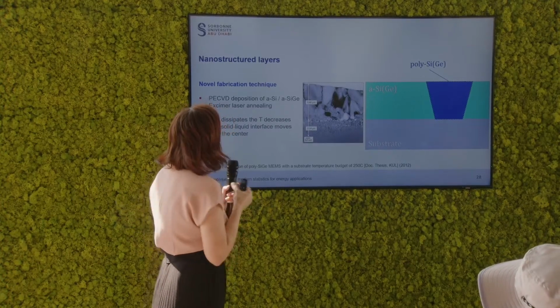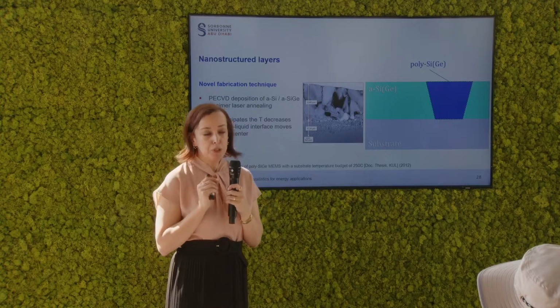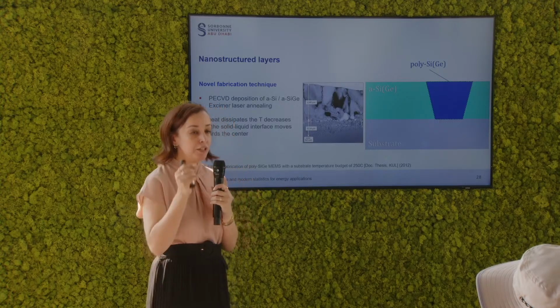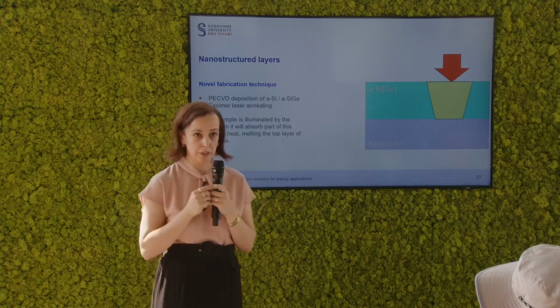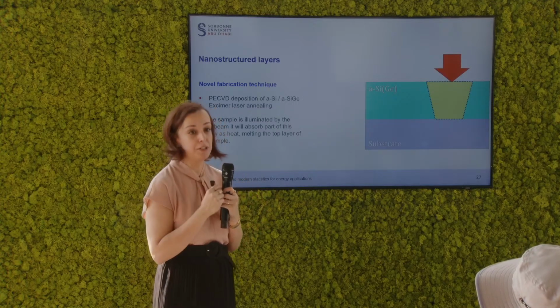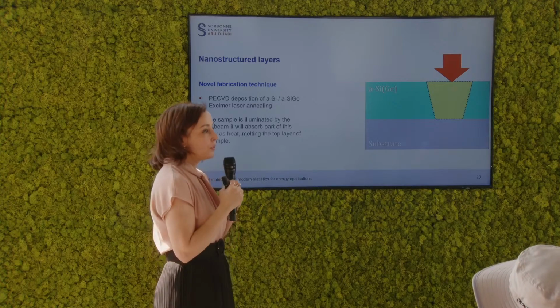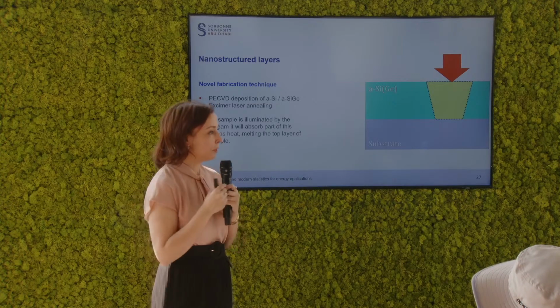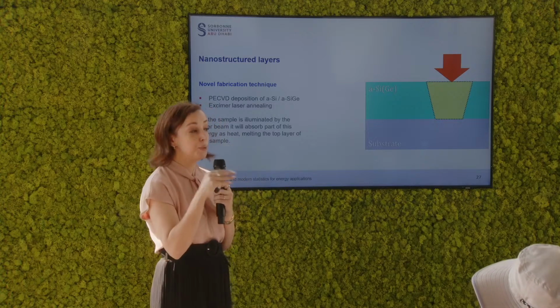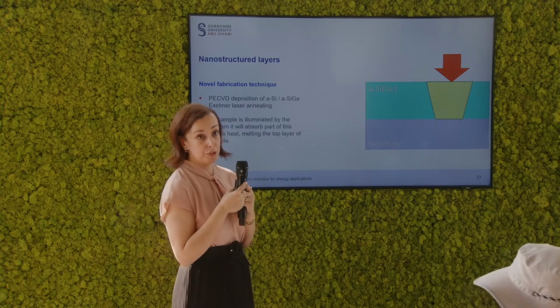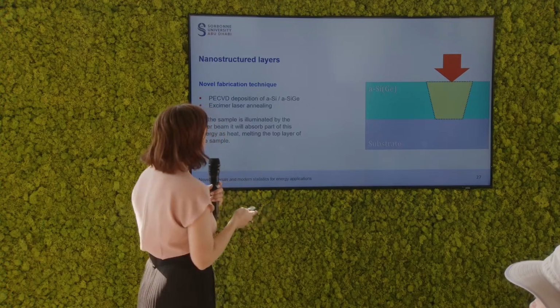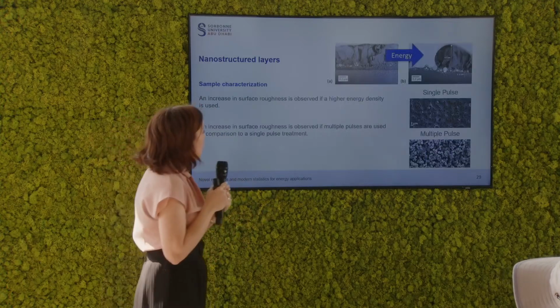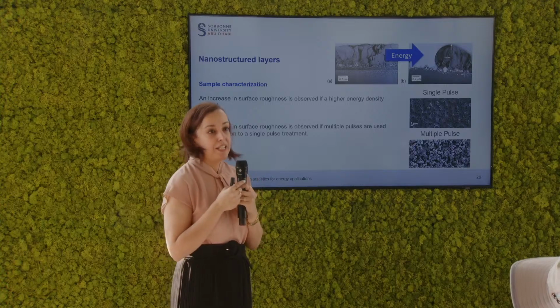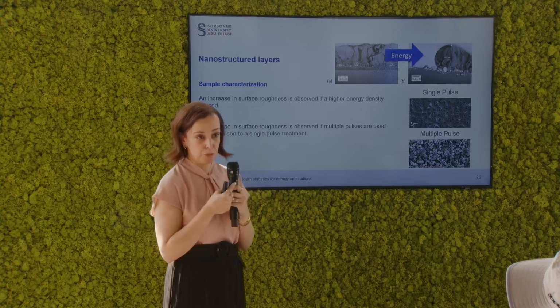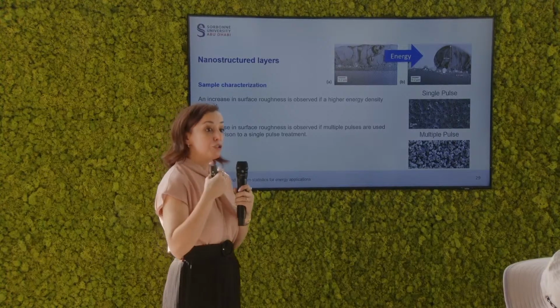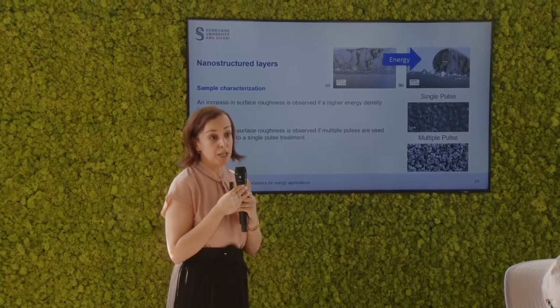It's important to note here that only the top layer of your material is subjected to the laser pulse. So in terms of a thermal budget, this is a low thermal budget process. So any underlayers that you have underneath will not be subjected to the laser pulse and will not be heated. Nevertheless, laser annealing is a harsh fabrication process, and we expect surface roughness to occur due to that laser pulse.